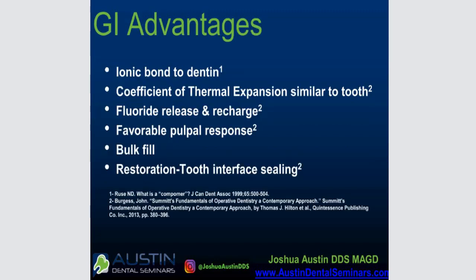So let's talk about the advantages of using glass ionomer, and there's quite a few actually. The number one, in my opinion, is the fact that we actually get a true bond to tooth structure with glass ionomer. So when you're talking about glass ionomer, if you want to get real technical about it, you're talking about a polyalkanoic acid polymer matrix. And there are carboxyl groups in that material that chelate the calcium and hydroxyapatite and actually form an ionic bond with the tooth structure. So it's really the only material we have that ionically bonds to tooth structure, specifically dentin.